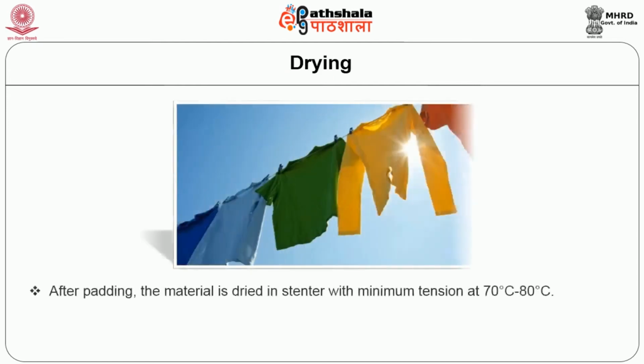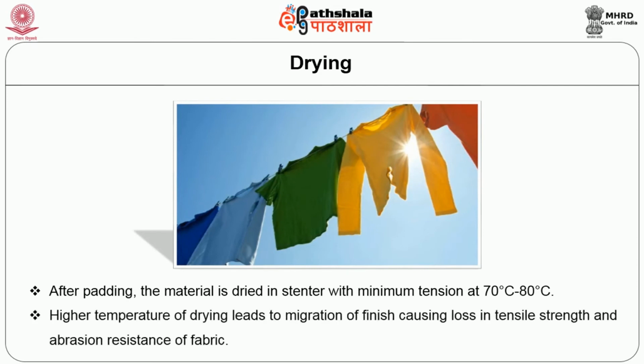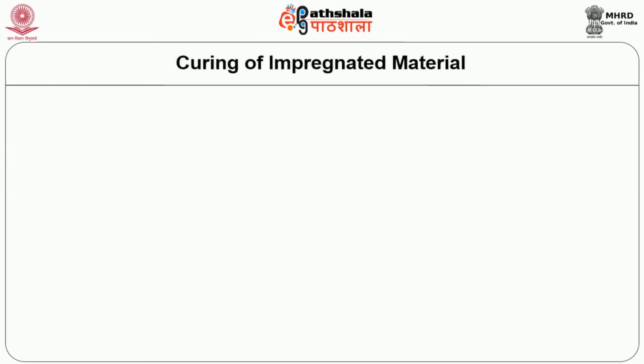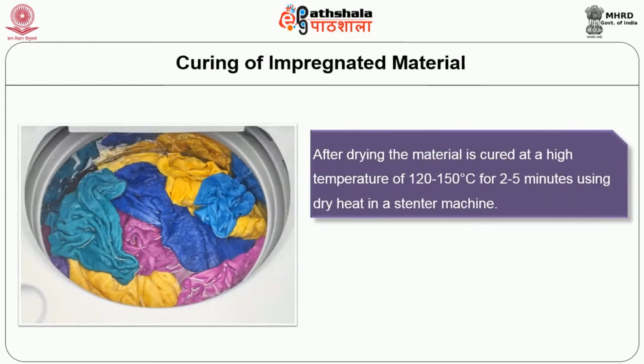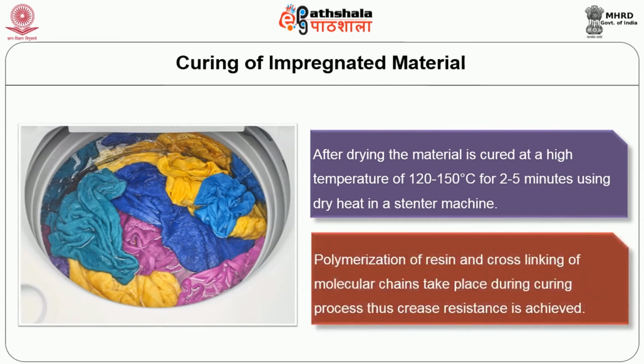Drying. After padding, the material is dried in stentor with minimum tension at 70 to 80 degrees centigrade. Higher temperature of drying leads to migration of finish causing loss in tensile strength and abrasion resistance of fabric. Curing of the impregnated material. After drying, the material is cured at a high temperature of 120 to 150 degrees centigrade for 2 to 5 minutes using dry heat in a stentor machine. Polymerization of resin and cross-linking of molecular chains take place during the curing process, thus crease resistance is achieved.